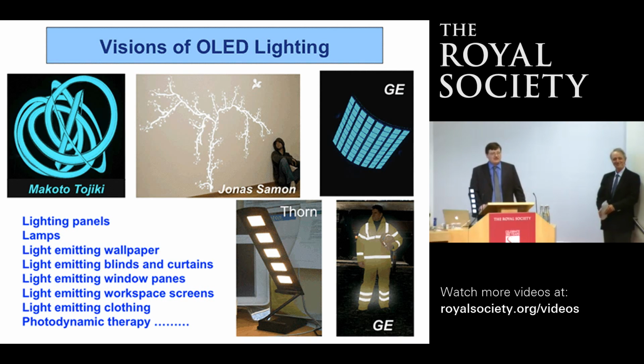Yes, that's obviously a very good question. Initially people were extremely worried about the lifetime of these materials because, as you say, it's well known that a lot of these materials suffer from a variety of degradation mechanisms. What's interesting is that with the original OLEDs that we made, the failure mechanism was actually losing the aluminium from the polymer. If we stripped that aluminium off with sodium hydroxide and put more aluminium on top of it, it would light up again. So that gives you some idea that not all organic materials are weak in that context.